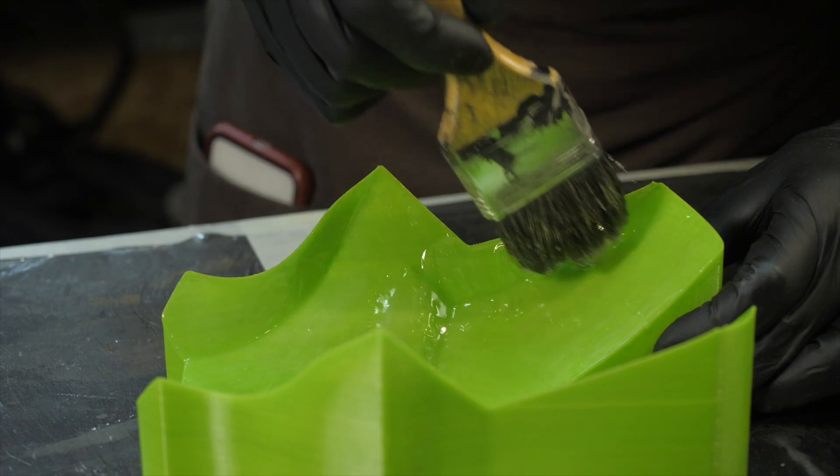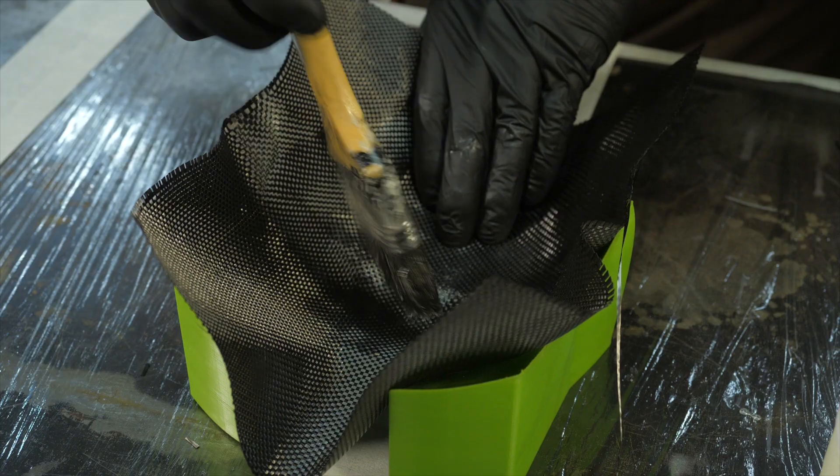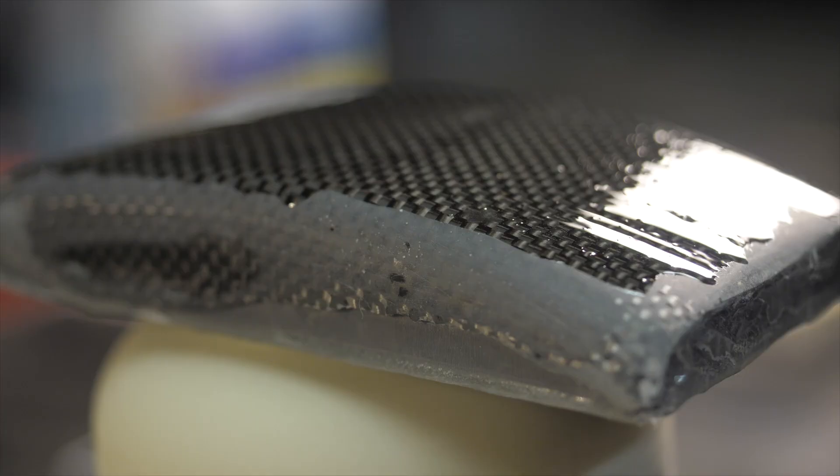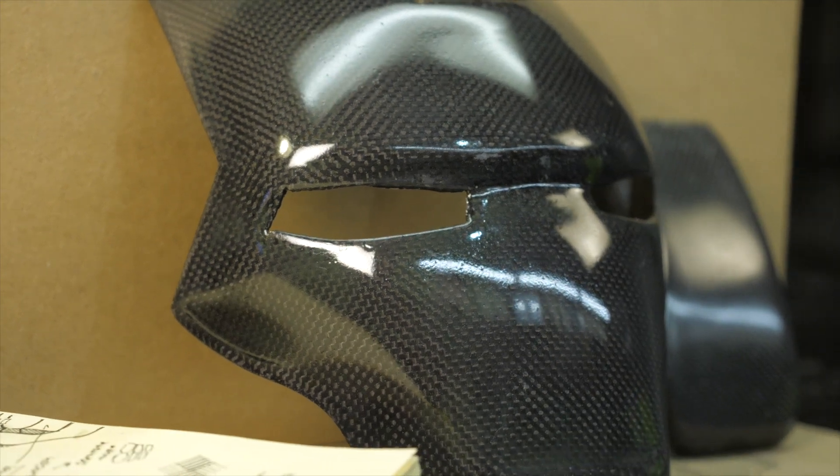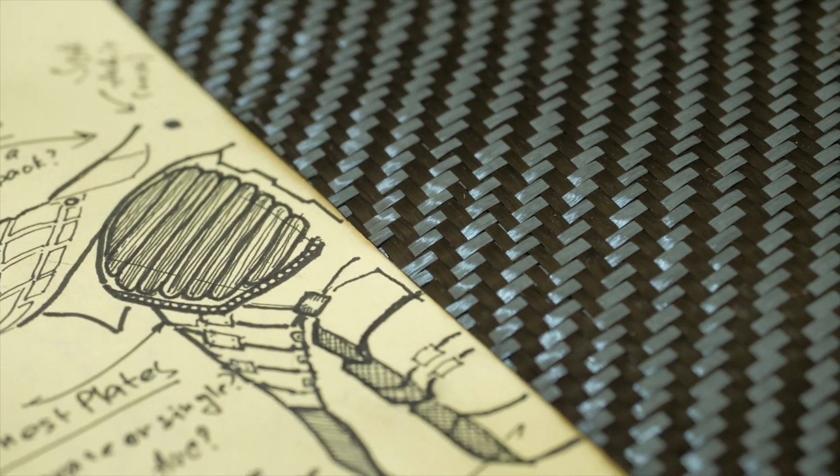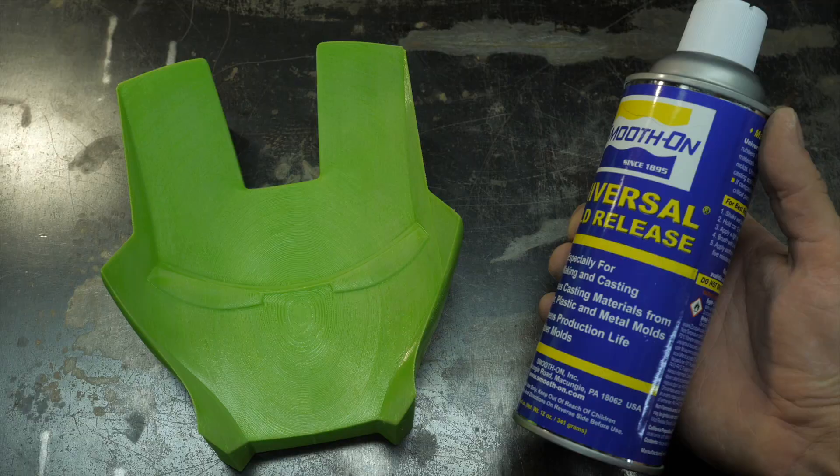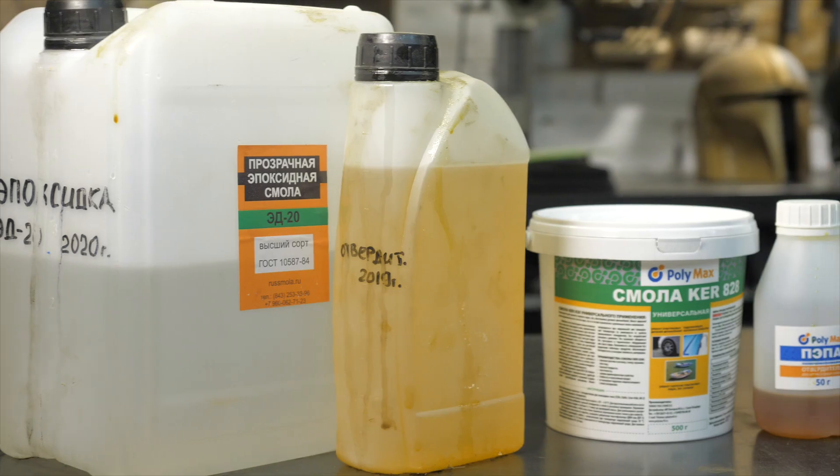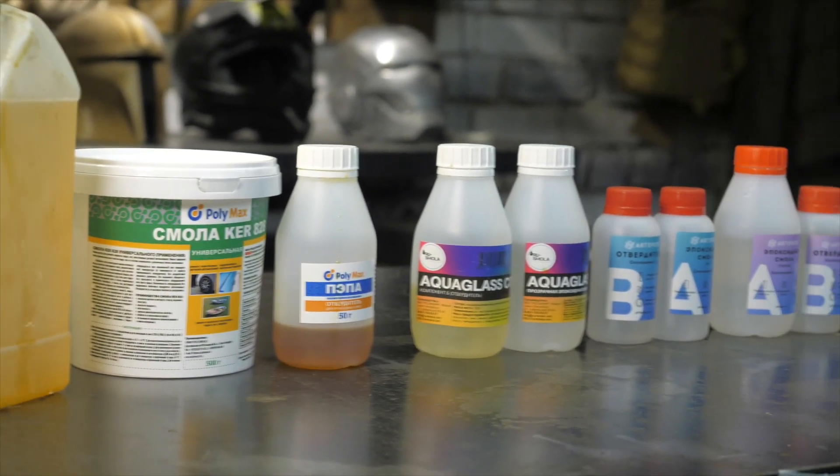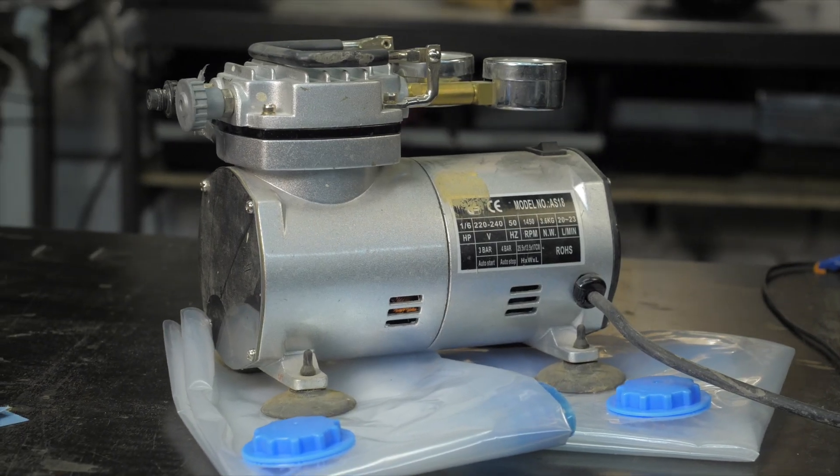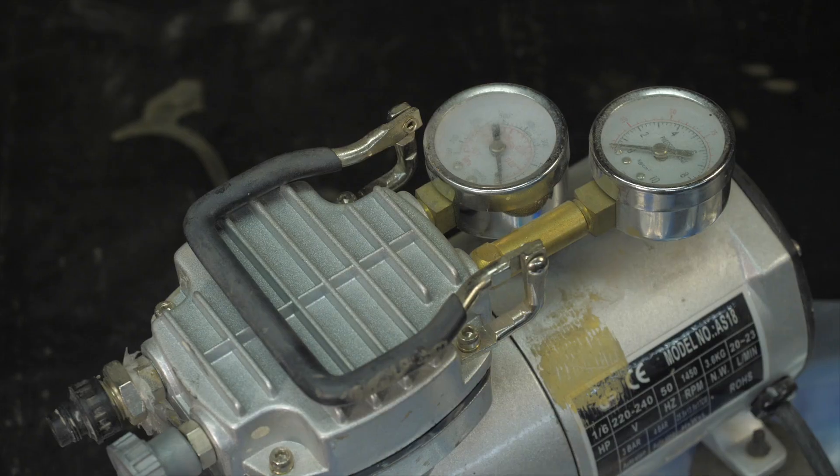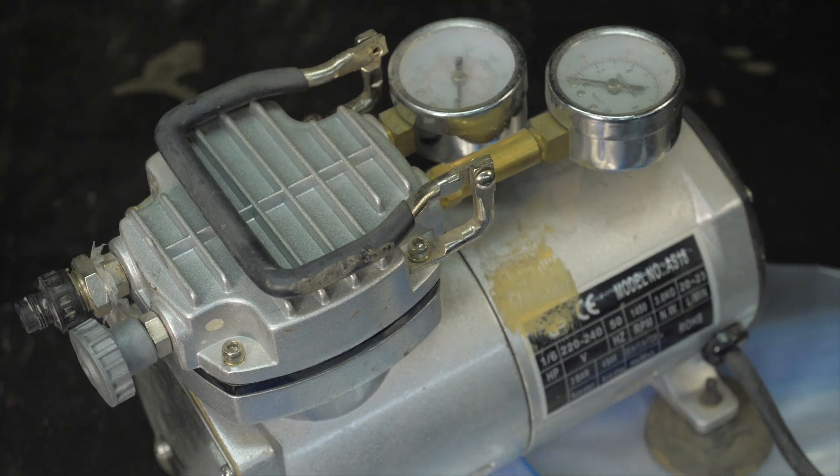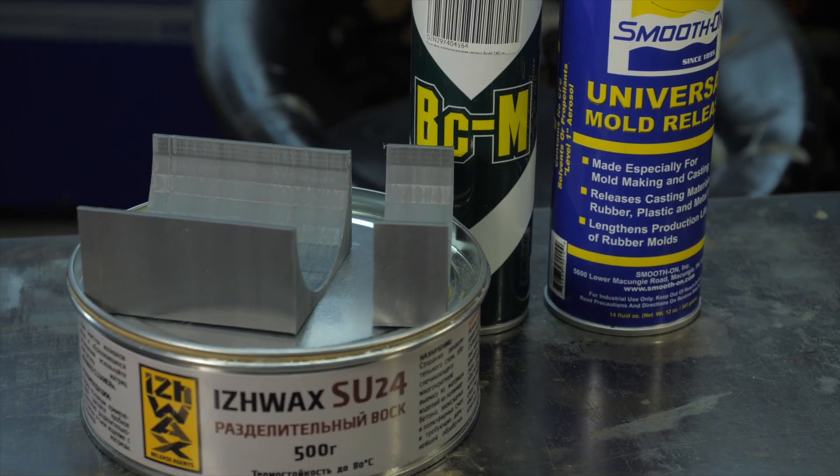Second problem, high quality laminating in molds is very demanding on the components. To create a high quality and smooth surface of the part, fabric with a specific weave is needed, expensive separating layer, which also doesn't always work and is hard to find, and epoxy resin of a very specific consistency, and vacuum compressor, bags and connections.